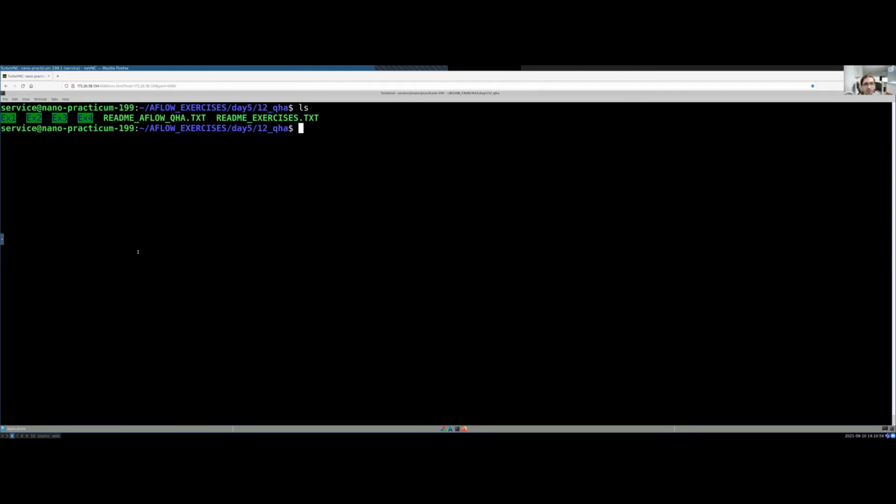So for example, if you do a 2x2x2 K-point grid in your supercell, you need to relax your structure with that times the supercell dimensions sometimes. Otherwise, you might get ghost forces. And APL does that automatically. You can look at the APL README to read more about what APL does.